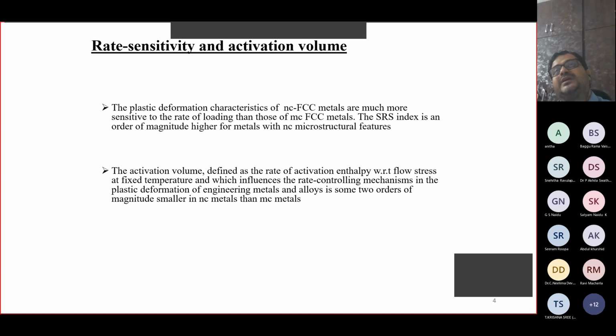Sometimes when you increase the strain rate, you will have an increment in the flow stress, in which case you will get positive strain rate sensitivity, so that your material is reasonably ductile. In other cases, when you increase the strain rate, your strength will come down. That shows negative strain rate sensitivity, and you don't want that type of material for any kind of application because there's some kind of plastic instability. You need to avoid that kind of negative strain rate sensitivity.